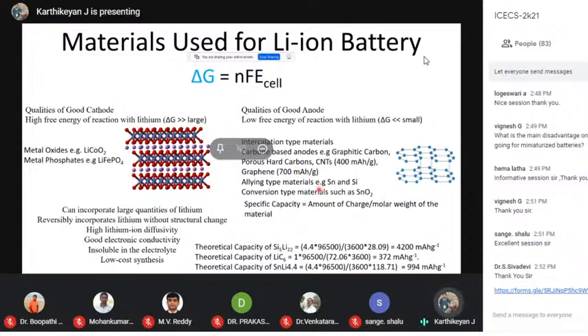We can also use other oxide materials like tin oxide. These are all conversion type materials. In this conversion type material, first the tin oxide reacts with lithium and forms lithium oxide, and then further lithium reacts with the tin and again forms alloying kind of things. As I told you, we do DFT calculations for understanding these materials. Here I have shown an equation, the Nernst equation, which relates the free energy of the reaction and the cell voltage. Here DFT is very effective in calculating delta G. So if you can accurately calculate the delta G of these lithium reactions with these anode materials or cathode materials, you can calculate the potential of the anode or cathode.